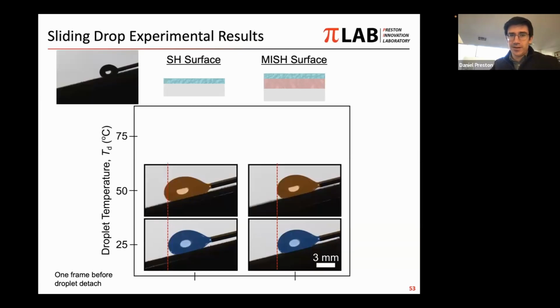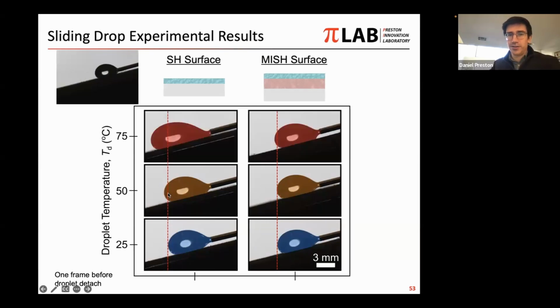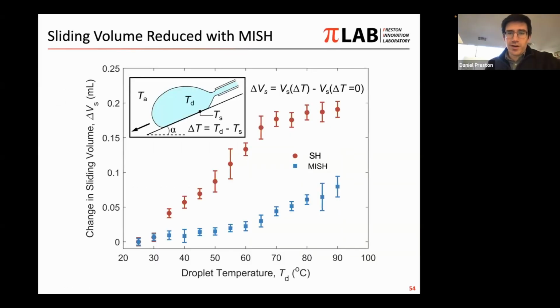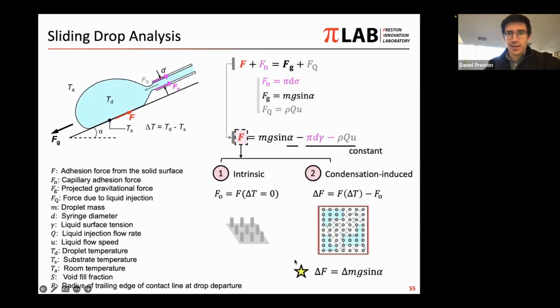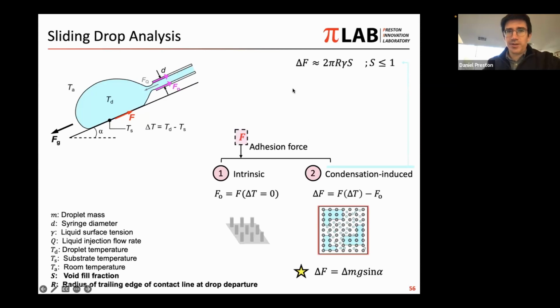But as we go to higher and higher droplet temperatures, we start to see increase in the departure size for the super hydrophobic coating only to quite large droplets, whereas that is minimized with this mesh surface with the thermally insulating layer. And so it's shown quantitatively here. These are just the changes in the sliding volume that we calculated through image processing versus the droplet temperature. And we can kind of understand that in the context of the model. And we can rearrange that, and we can also think about the limits or bounds of the model.